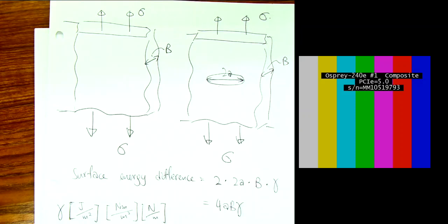We derived that stress concentration around the crack tip from Inglis, and we have that radius of curvature at the crack tip explicitly in the equation, right? So that depends on the sharpness of the crack. Now, that's very difficult to use, because we never know the radius of curvature around the crack tip, right? That's very hard. How do we measure that? It can be atomically small. I mean, sometimes it can be microns, but we don't know, right?